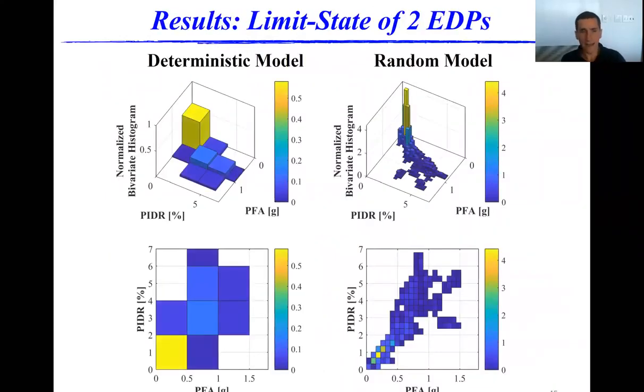So now we can look again at our deterministic case versus our random case, and we can start to plot the estimated joint PDFs, which are the normalized 3-dimensional histograms. So here I have the random case, and here I have the deterministic case. And we can immediately see that the deterministic histogram is much coarser than the random histogram, and this is again due to significantly fewer sample points, only 50 here versus 2,400 here. So the densities are not only different in terms of the peak estimates in the same region.